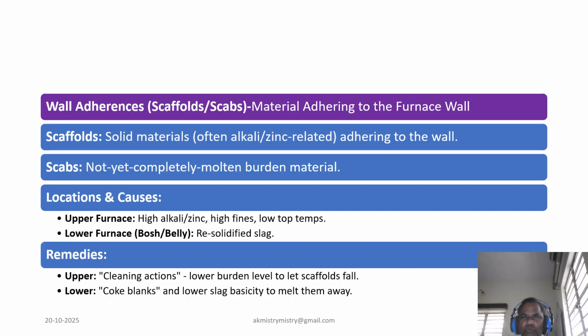Now, those recirculating elements often end up here as wall adherences. We have two main types of scaffold, which are solid materials stuck to the wall, and scabs, which are burden material that haven't fully melted. Their location tells us the cause. In the upper furnace, it's typically high alkalis, zinc fines, and low temperature. In the lower furnace, it's often resolidified slag.